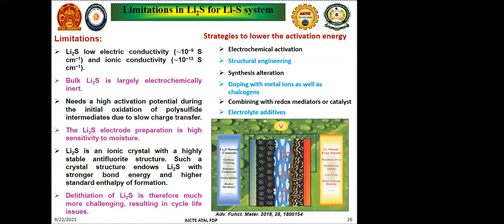So there should be another way to recover from the oxidation of the polysulfide, or to reduce the generation of the polysulfides, because when the polysulfides generate, there is very high resistance or slow charge transfer. Also, the major problem in the Li2S system is that it is very moisture sensitive. So every time we have to work in a glove box, so we have to think of that problem also.